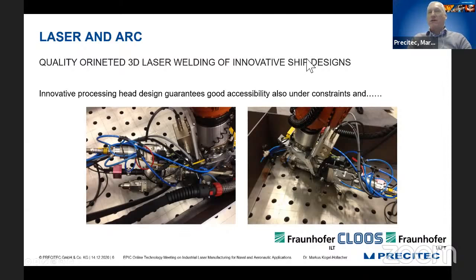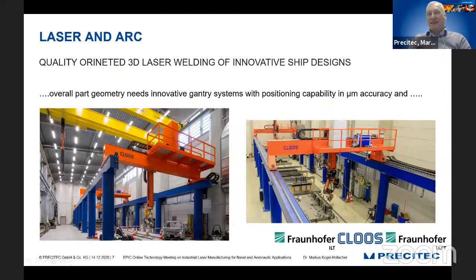So the idea was not only to weld in typical weld positions, so in all the weld positions which are happening in shipyards. So vertical, horizontal, going up, going down. That's why again we oscillated a little bit the laser beam with the robot, and we had a very innovative seam finder. I will come to that later. But this innovative processing guarantees good accessibility also under constraints, and this is important for Damen.